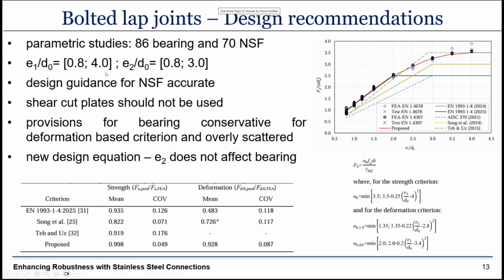So we varied from 0.8 to 4, and the edge distance, so the distance from the edges perpendicular to the direction of the applied load, was varied between 0.8 and 3. We saw that in all cases, the design equations for net section fracture were very accurate. The shear cut plates, we did not manage, obviously, to replicate the results for 14678 because of the very complicated conditions close to the edges due to the localized hardening. So we validated the model only for water jet cut specimens.